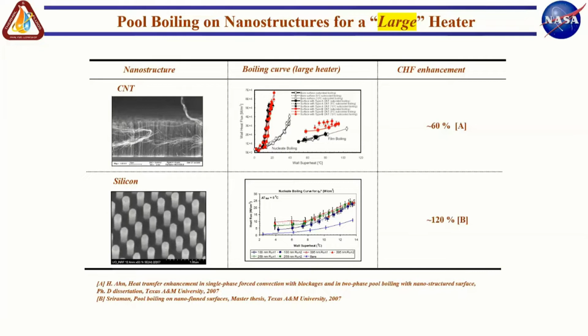And so if you plot the boiling curve, which is your wall heat flux plotted as a function of wall superheat, the lines marked in red and filled black icons are the carbon nanotube coatings. So one is 10 micron, and the red marks are the ones that are coated with 25 micron carbon nanotubes. And there are a lot of nuances here, but in the interest of time, I'm just going to focus on the primary nuance here, which is the critical heat flux got enhanced by 60%.